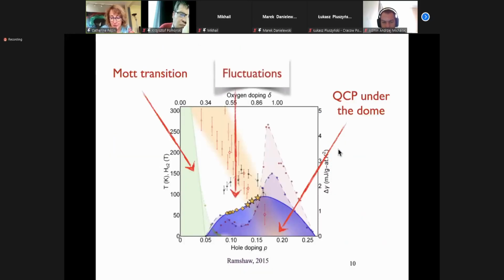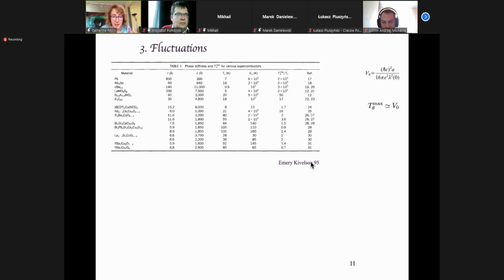So last one, fluctuations. So it's also a very old idea. So here the paper is from 95, but Emery and Kivelson, and not only them, I mean, a lot of theoreticians have gone to this idea, that fluctuations have to be there. So basically what they did is they supposed that we have a BKT transition for the cuprates. Namely, you get a mostly two-dimensional superconductor, and you get the transition temperature by forming vortices. So it's vortex, anti-vortex that form pairs of topological defects, and you will reach TC this way.